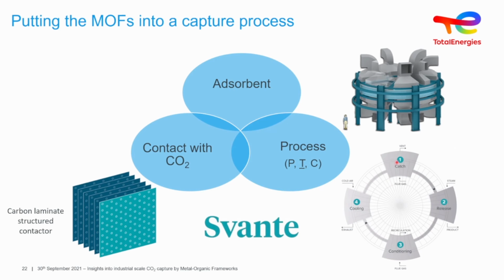It's basically a 4-step process: catching, releasing the CO2, and then drying the system and cooling afterwards. So this is what they're doing, a 4-step process. And this cycle is of interest because it takes 1 minute. And this is an idea of what would happen on the full scale. So a temperature swing process carried out under 1 minute. So this is of interest if we want to have compact systems, but also of interest for full scale, because we can have 3 or 4 of these next to each other, and they take up the same footprint as an amine scrubbing unit, for example.